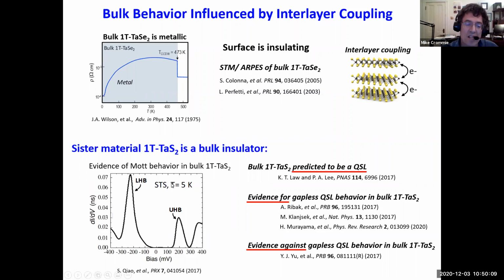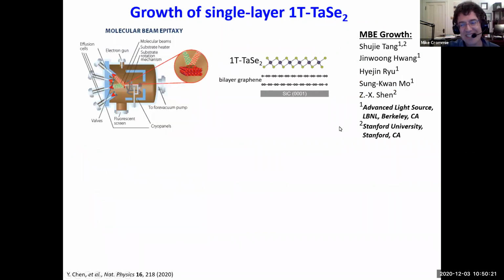That was our goal here: to go to the single layer limit to get rid of that interlayer coupling. Now, actually, the material I wanted to study was 1T TaS2, but my MBE growers wouldn't grow it because they hate sulfur. MBE guys hate sulfur, but they love selenium. They said they won't give us TaS2, but they'll give us TaSe2. So that's what we studied. We used MBE to grow our samples because MBE is a nice way to grow very clean samples, good for STM and surface science measurements.